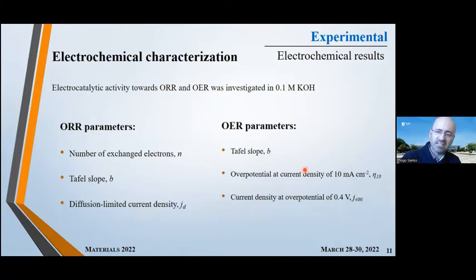So as for the electrochemical characterization that we've done towards ORR and OER, we did this in an alkaline electrolyte because we want to perform this in alkaline media, and we use 0.1 molar KOH. So we evaluated the activity of the materials by determining different parameters for oxygen reduction reaction and for oxygen evolution reaction. So the number of exchanged electrons, that should be close to 4 if we want the direct, complete oxygen reduction reaction. We determine the Tafel slope and the diffusion limited current density. As for the OER, we determine the Tafel slope, the overpotential at current density of 10 milliamps per square centimeter, and the current density at an overpotential of 400 millivolts.